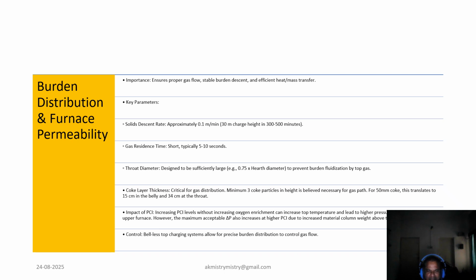Coming to our next slide, which is basically on the precise burden distribution, which directly impacts gas flow and descent stability. It also takes control of efficient heat and mass transfer within the furnace. Now, burden stock charging programs are complex and require detailed modeling. This includes measuring material falling curves, traditionally by filming material trajectory against a fixed grid, and more recently using laser nets to observe falling angles.